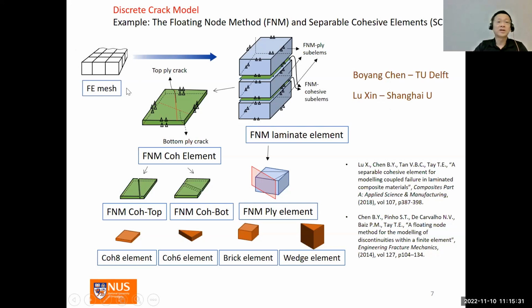So if you imagine a finite element model, let's say here on the top left corner of a composite laminate, upon damage initiation, the nodes are seeded onto the brick elements to simulate matrix cracks by partitioning the elements. So the elements here, for example, a partition element in this plane. With this will be the matrix crack. So the word is called floating node because the nodes are floating before they are seeded and, if you like, assigned to an element for partitioning.